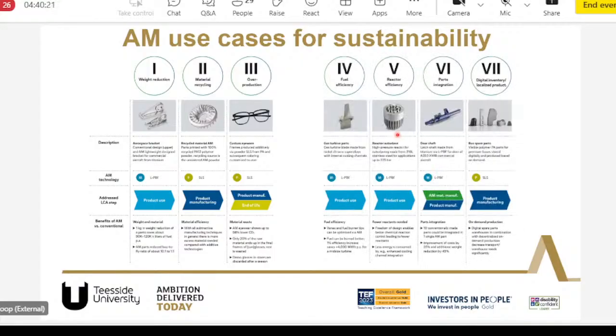These are some of the case studies where additive manufacturing has been used for sustainability. If you see the aerospace bracket case, which are printed using additive manufacturing, then if you use laser powder bed fusion in the product stage, 1 kg reduction in the weight results in a saving of 90K to 120K liters of fuel per annum. And the AM part reduced the buy to fly ratio from 10 to 1 down to 1 to 1. So there is significant cost savings, significant material savings with this.